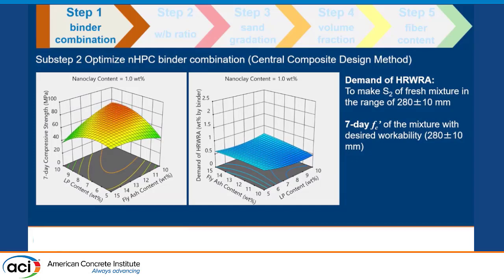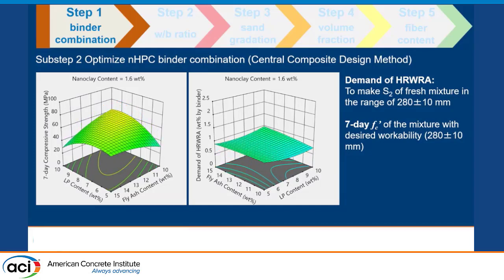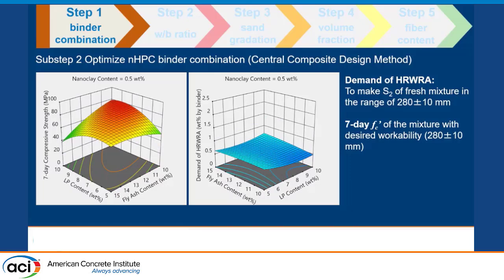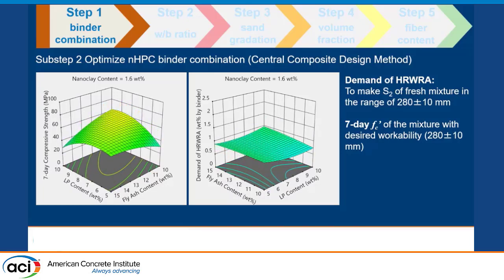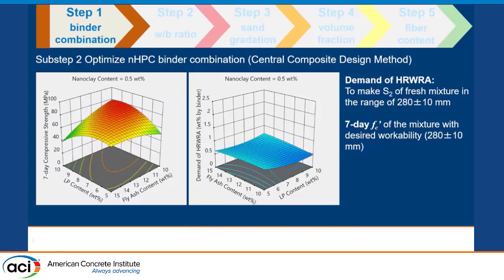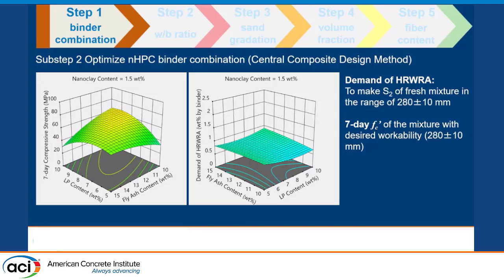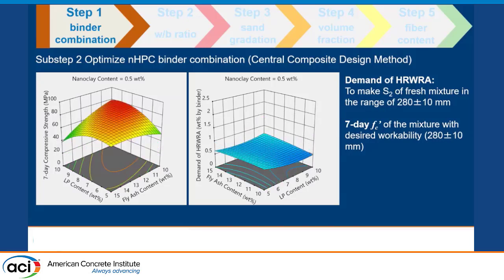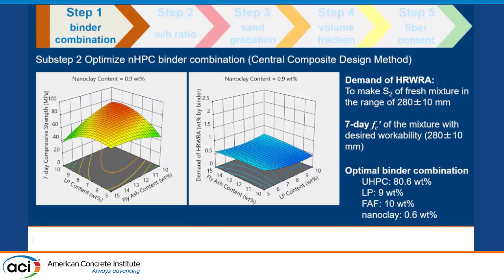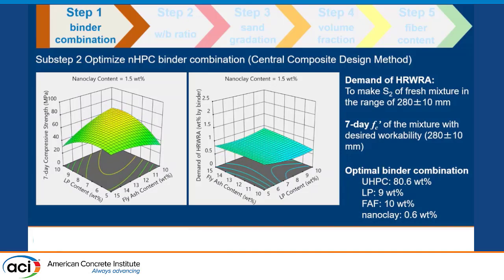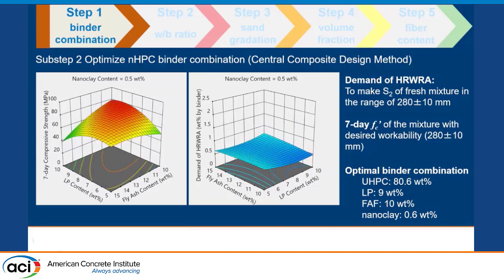So now we can optimize the nHPC binder combination. As we can see here, with the increase of the nanoclay content, the compressive strength will decrease, while the demand for high range water reducer in the mixture will first decrease and then increase. So with the help of Design Expert software, we can come up with the optimal binder combination of this number.